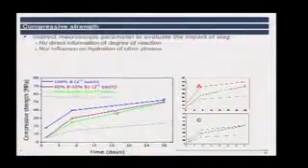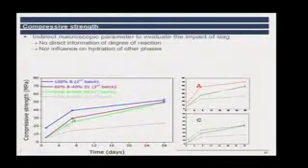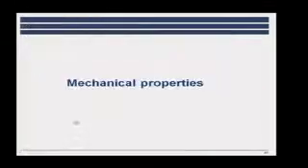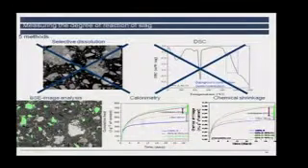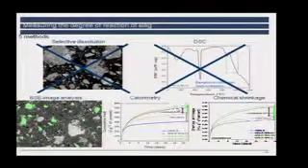Now, what was particularly interesting in this case was we had two different slags, and we see that in terms of strength, the contribution from this slag, the purple one here, slag 1, was quite a bit more than this slag 8. This was, in fact, the reverse of what was happening in terms of hydration. You can maybe see here that the green one is actually reacting more and reacting faster than the purple one.